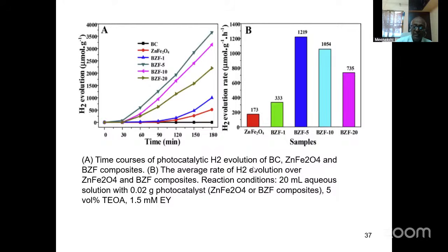This is another photocatalytic hydrogen evolution using biochar with zinc ferrite. That's why I told you this is a magnetic biochar, because we are using iron, zinc ferrite. That Fe3O4 is also a magnetic biochar. For zinc ferrite, they used compositions of 1, 5, 10 and 20% zinc ferrite in the biochar, and looked at hydrogen evolution. You can see that 5% zinc ferrite biochar is found to be most efficient, producing the maximum amount of hydrogen compared to the other ones.